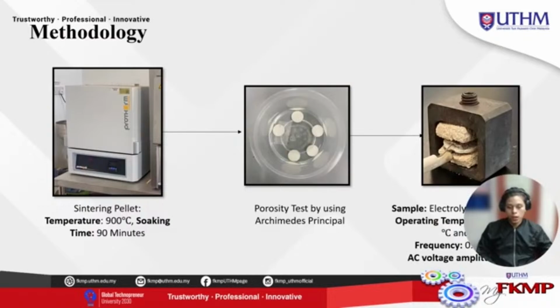Before this, the pellet will be fragile if we do not do the sintering process. Sintering is at 900 degrees Celsius, and the soaking time is 90 minutes. And then we go to the porosity test by using Archimedes principle. We soak the pellet in ethanol for 24 hours.